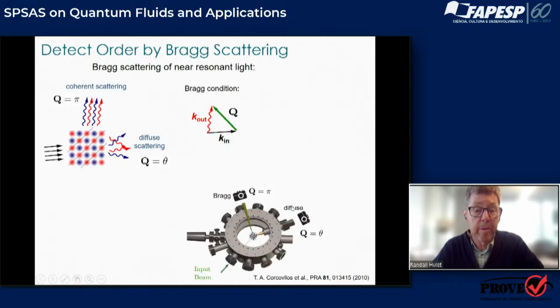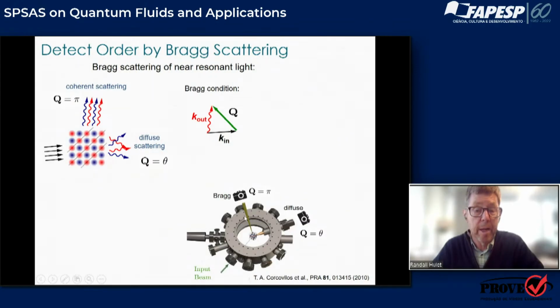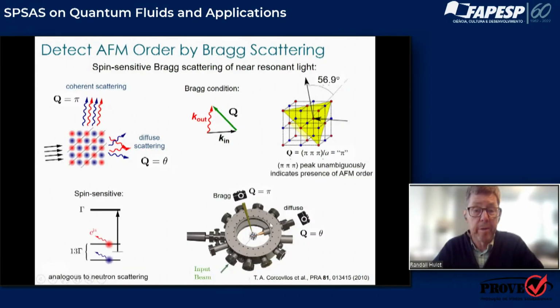This is what the experiment looks like. There's an ultra-high vacuum chamber. We then send in light at the Bragg angle, and we look at the corresponding Bragg angle. I guess the light comes in this port, and we look at the coherently scattered light on this camera. And we also put a camera at a random angle. We call that random angle theta. We expect to see coherently scattered light coming in this direction, and only diffuse scattered light coming in this direction. And that's the Bragg condition. So the Bragg condition turns out to be achieved with this wavelength of light at 57 degrees.